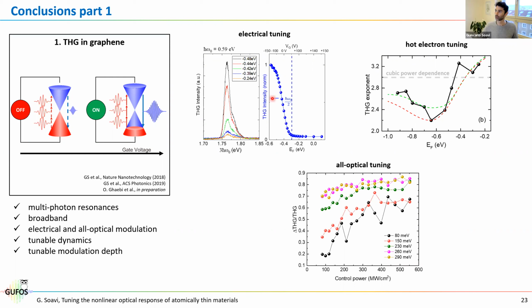But we can also achieve all-optical modulation, and all-optical modulation can be given either by electronic temperature, and this explains this deviation from the cubic dependence in third harmonic power-dependent experiments, or it can also be due to Pauli blocking, and here there is an interplay between Pauli blocking and electronic temperature, depending on the value of the Fermi level, or let's say depending on the doping of the material.